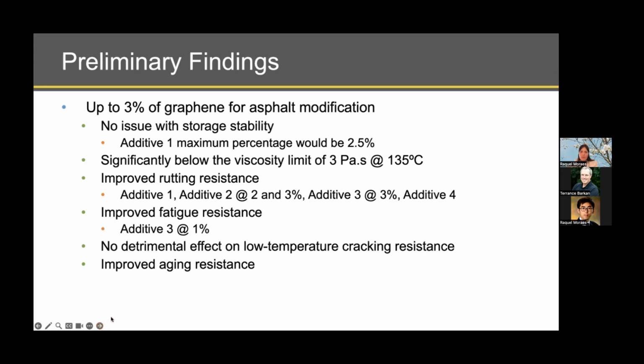We saw improved rutting resistance, indicating, in simple words, material being harder or stiffer than the base binder for additive 1 at all doses, additive 2 at dosage at 2 and 3%, and additive 3 at dosage of 3%, and additive 4 for all dosages.